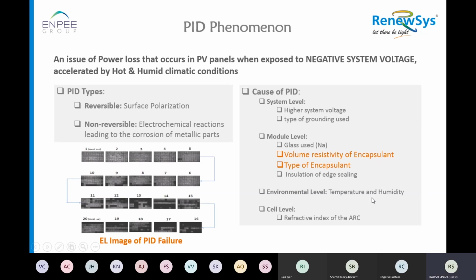Environmental condition, as we said, depends on temperature and humidity. So if we are making a module or EVA for a climatic condition which is hot and humid, we are more careful to make the PID resistance of EVA better or higher. Whereas if it is to be installed in a cool and dry condition like Europe, probably this is not a key property to control in an encapsulant. At cell level, it is controlled by increasing the ARC, the anti-reflective coating, which is done during cell manufacturing. This is nothing but increasing the refractive index of the ARC coating.